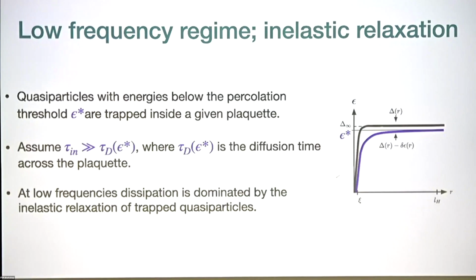So let me start with the 10 minutes, even seven. Okay, quickly, low frequency regime. So the key point is that quasi-particles with energy below the percolation threshold are trapped inside the given vortex plaquette. They cannot diffuse. And so at the lowest frequencies, the dissipation is dominated by these trapped quasi-particles.